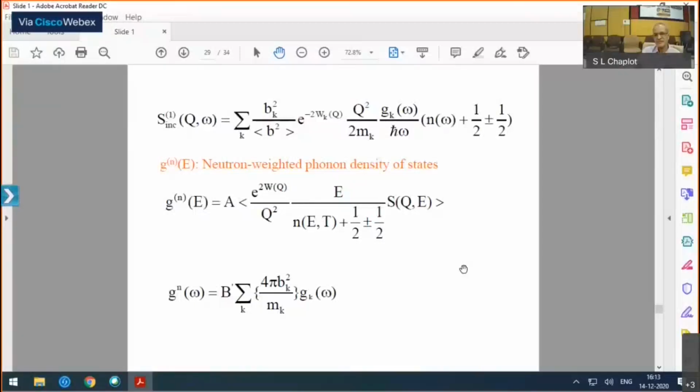The good part is that vanadium's coherent scattering cross section is negligible, and because it has essentially only the incoherent scattering cross section, there are no complications because of the structure or the collective dynamics. Therefore, the dependence on the wave vector is very simple.